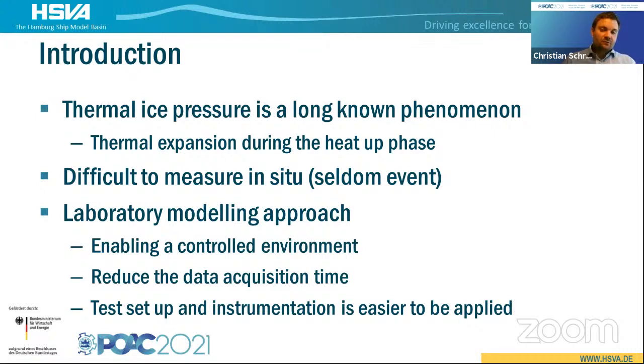Generally, thermal ice pressure is a quite long-known phenomenon. It happens when ice is in a restricted area and it's heated up from relatively cold temperatures up to the melting point. Outside, it's relatively difficult to measure because it's a relatively seldom event and you never know exactly when it will happen. So our approach was to bring nature into the laboratory and model this thermal ice pressure within our laboratory scales in a controlled environment, which can reduce the data acquisition time, and instrumentation can be more easily applied and used for just a shorter time period of measurements.